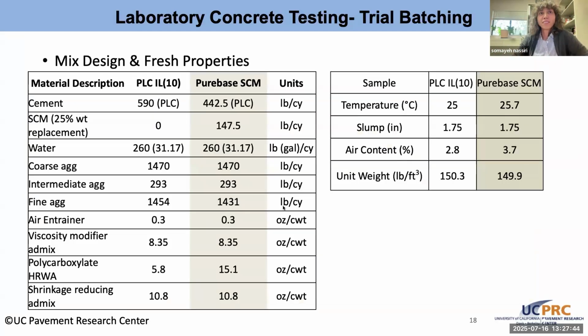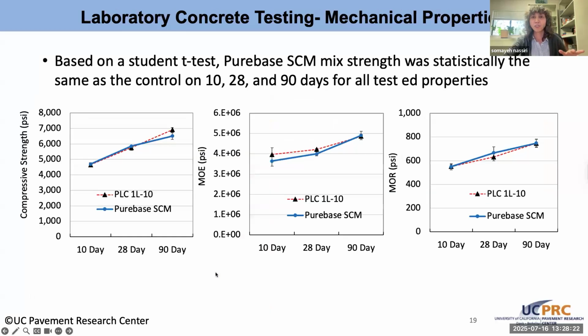So back to our example, case material here being pure base, we use a control. Here's our trial batching. This is our concrete mix design. We look at admixture demand here, incorporate a couple of water reducing admixtures, and that is one of our areas of focus: water demand, admixture demand, while making sure durability and cement hydration are in check. So this trial batching really helps us narrow down and finalize our mixture formulation, looking at some of those fresh properties and trying to match target slump, target air, while finalizing and verifying admixture demand.